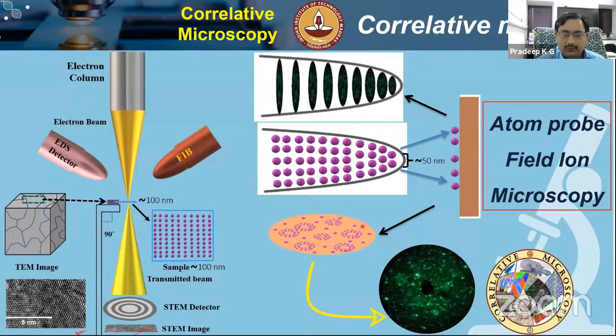With the existing tools, it is very difficult to identify the short range orders. If you have 3 atoms, 4 atoms forming a cluster, and 1 atom is potentially missing because of detection, we may miss out on this short range order information. Large data sets over different sequences of imaging would enable us to identify these short range order clusters using a computational tool, which will help us understand the material's properties in a better way.